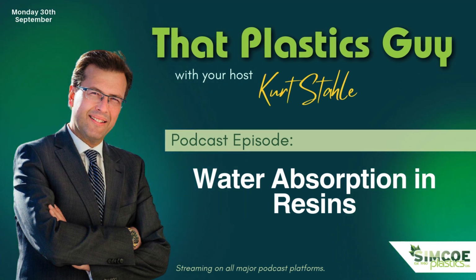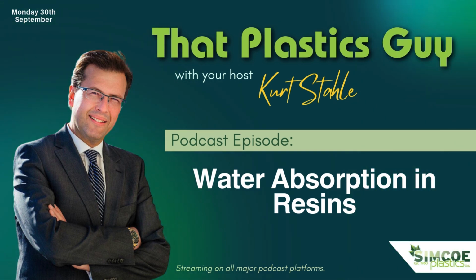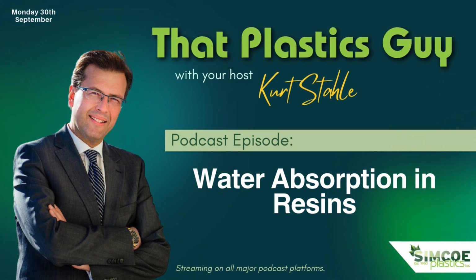High impact polystyrene: dry weight 0.05 of a percent, the equilibrium maximum moisture content 0.15 of a percent. So it's still very little. Could that cause you problems again on those ultra humid days? Yeah, absolutely could.